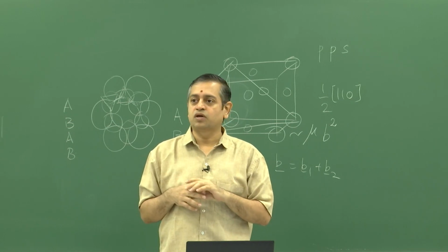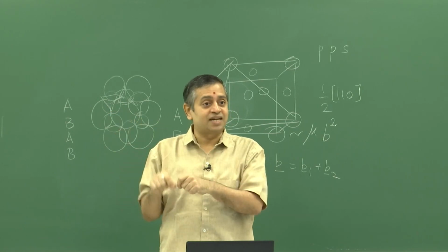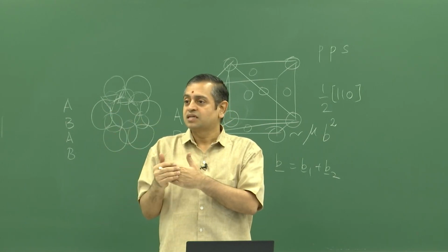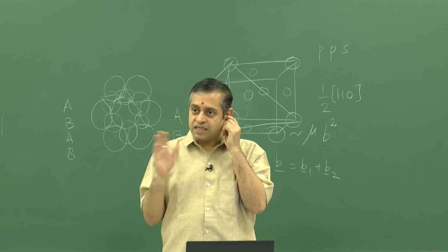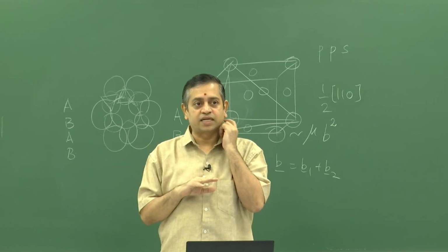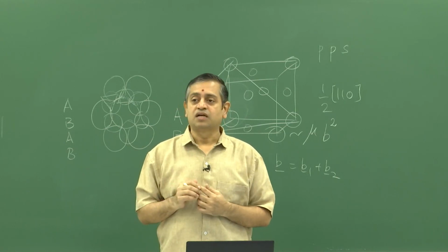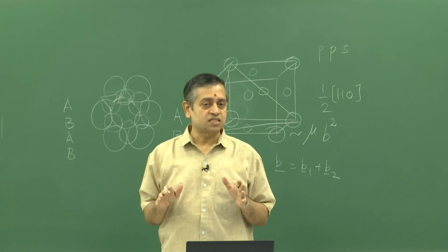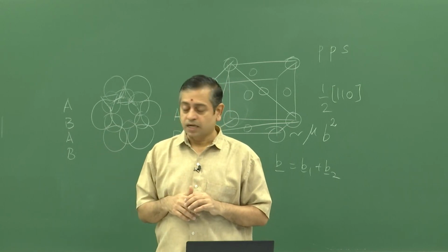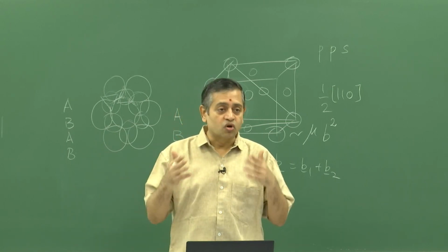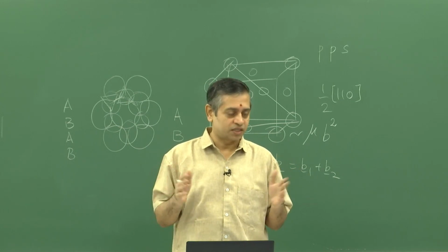So, to be consistent, that is why you do the free energy evaluation and stacking fault energy for this potential at that temperature, because that is what the actual system is experiencing, and that is how it is giving some deformation behavior. So, to make the correct connection between what is happening and what the energetics is, it is very, very important to evaluate all the quantities using the same potential, which is not the standard practice in the literature. Sometimes people take values from experiments or first principles and start interpreting. That can lead to problems, especially because you do not know what your EAM potential actually is like for this particular quantity. So, it is better to evaluate.